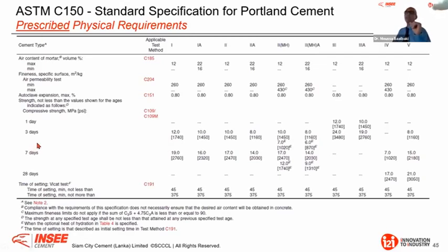I will explain to you why. But if I look, generally speaking, at this table in terms of compressive strengths, the minimum requirement is 32.5. But as I said, they don't mention 42.5 and 52.5 as we have in the EN standard. According to ASTM, the minimum requirement will be 32.5. Okay, and they test at 3 days and not at 2 days. Only 1 day is for type 3, and this is for high early strength cement.